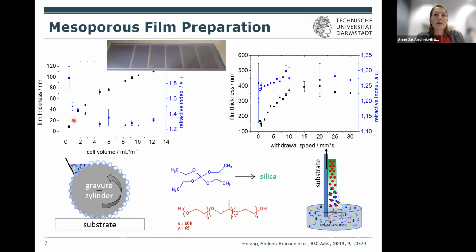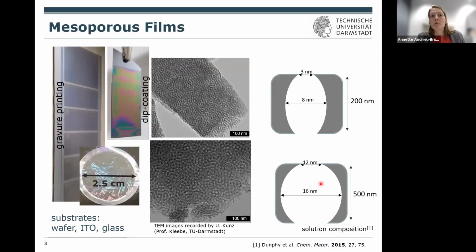You can see here that the film thicknesses can well be designed in both cases. And if you do this with a solution, and I will not explain the sol-gel chemistry in detail, but basically you have a silica precursor molecule and you have templates, you have an assembly process, and afterwards you just calcinate the block copolymer template out, and this leaves the pores. And then this is what you get. So this is the macroscopic view of the dip coating, of the gravure printing. We could show that we can transfer these films, although they are not that stable if you have them in hand like this.